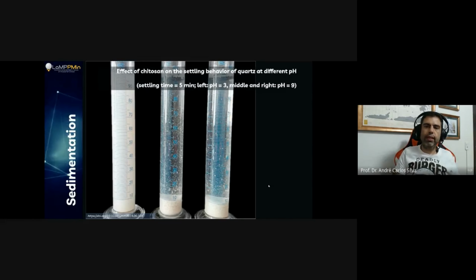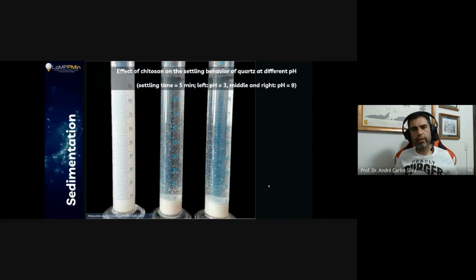So then again, when we change from one cylinder to the other, what I'm seeing on my left-hand side is a cylinder with pH 3. And the settling time allowed was 5 minutes, okay? So even after 5 minutes, I can't see a solid interface. And one thing that I can see for sure is I have material in all of my cylinder.